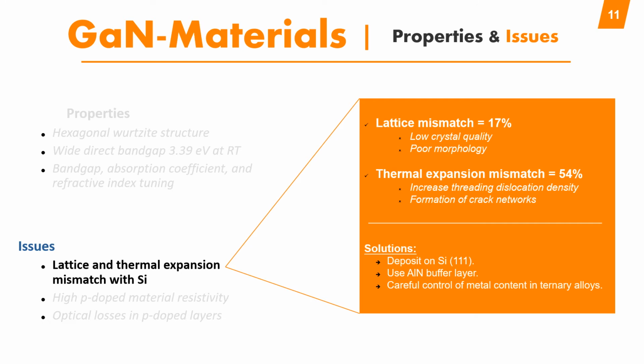Actually, when depositing gallium nitride over silicon substrate without careful control of the deposition process, we could have low crystal quality and poor morphology. And the thermal expansion coefficient mismatch is 54%, which is very large. This allows the increase of threading dislocation density, which is not desired at all for such a light emitting device, and it also allows the formation of a crack network.